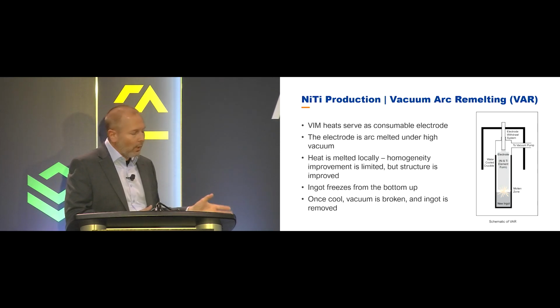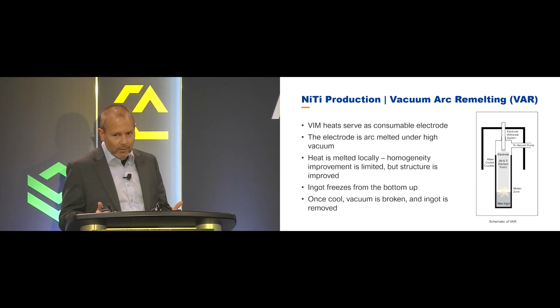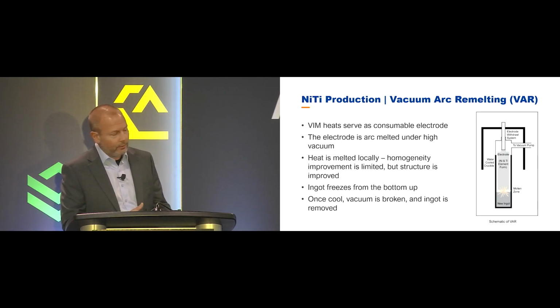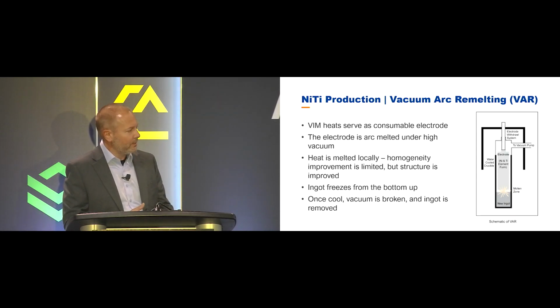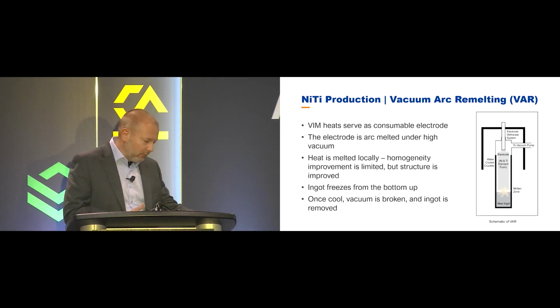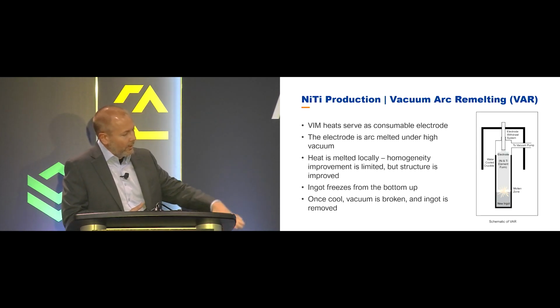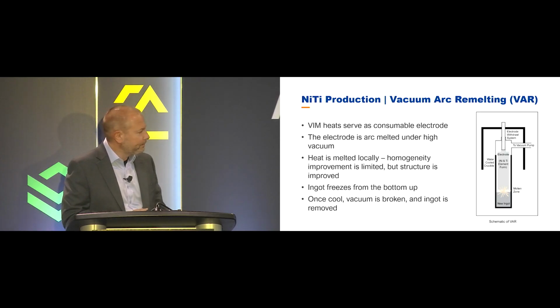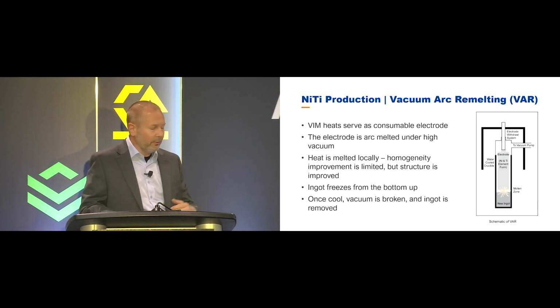So why are we doing this? A couple reasons. One, because we can take 9 small VIM ingots and make them into one, so we can process a bigger ingot with a larger lot size. The other reason is to control the structure. So we have a controlled solidification rate. We control, again, that ram speed, so we're allowing that liquid material to fill every void as it freezes from the bottom up. Again, there's different ways to do it.